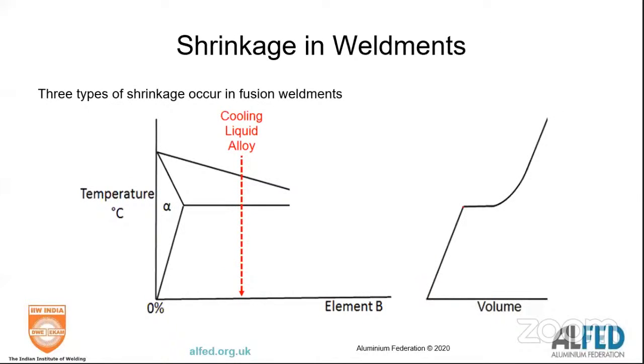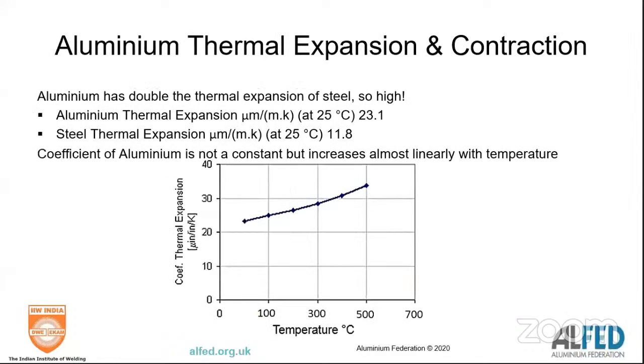In fusion welds, there are effectively three types of shrinkage. So you've got liquid metal cooling, then you've got the solidification cooling, and solid cooling. Now, aluminium has very high thermal expansion, so consequently very high thermal contraction, very roughly double that of steel. We're fortunate in aluminium, it's almost a linear relationship with temperature. With steel, it tends to sail away, but with aluminium, although we have high thermal expansion, it's almost a straight line relationship.